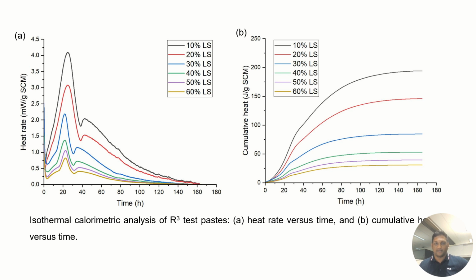The increased aluminate provided early false setting by combining with all available silicate and calcium ion, while the excess sulfate at this stage could not react to form ettringite as the C3A phase of the cement reduced with the partial replacement. Therefore, the secondary hydration peak reduced with the reduction of cement, and the susceptibility of internal sulfate attack was highly reduced at high replacement of cement.